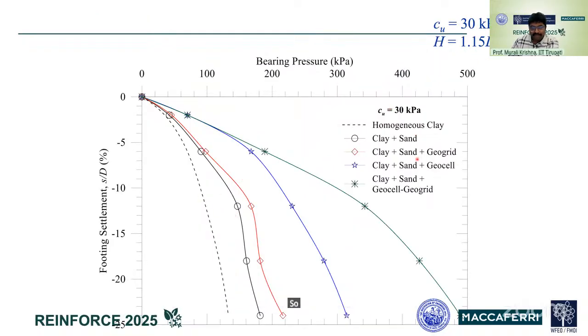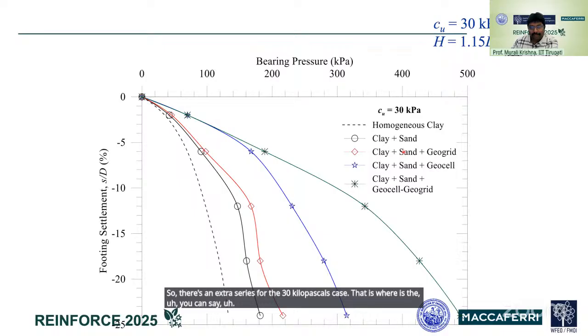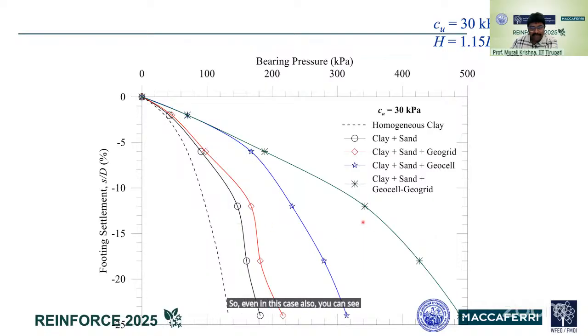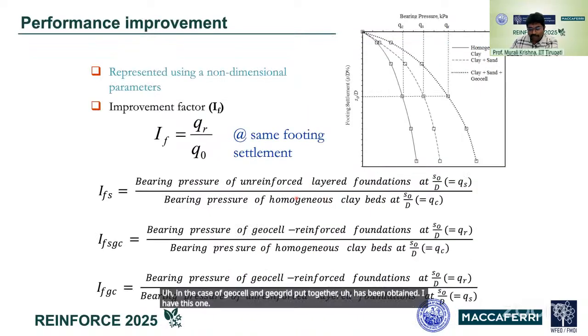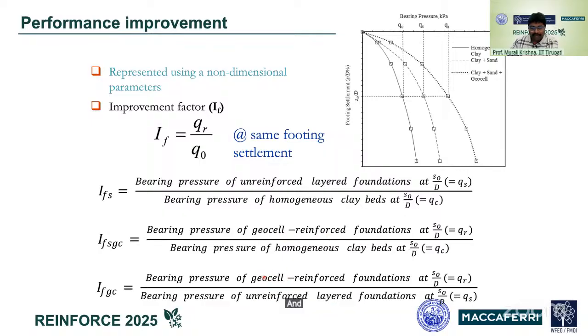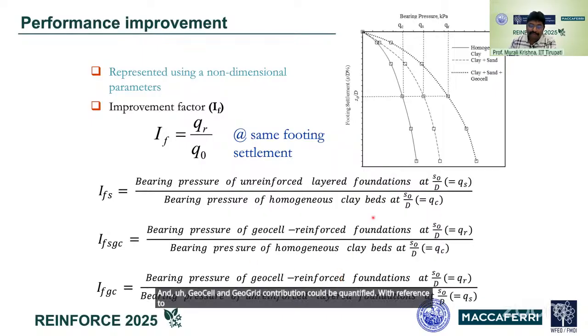So this is the next series for the 30 kilopascals case, which is a medium stiff clay, what we can say. So even in this case also, you can see very significant improvement in the case of geocell and geogrid put together. So similarly, the very dense soil or soft strips also we can improve. The contribution of different things, either sand layer contribution, geogrid, geocell contribution, and geocell and geogrid contribution could be quantified with reference to different reference parameters.